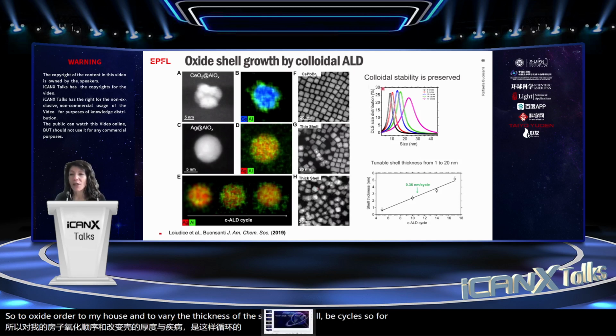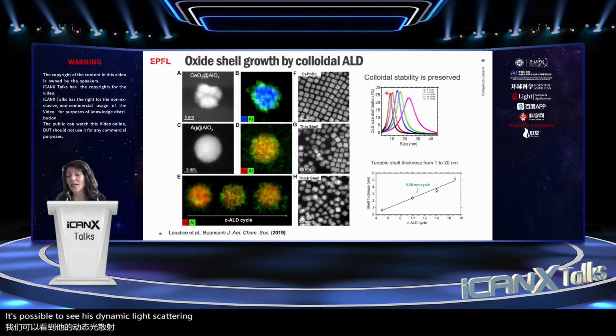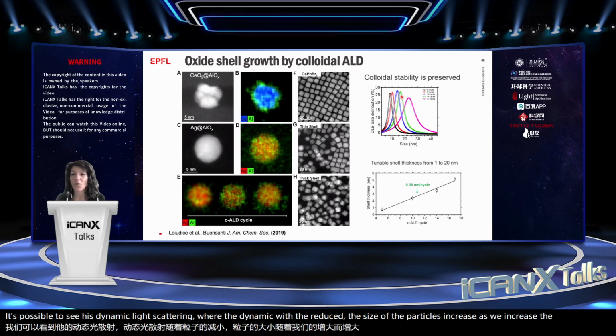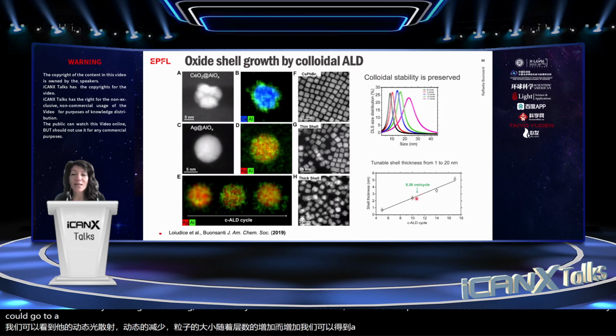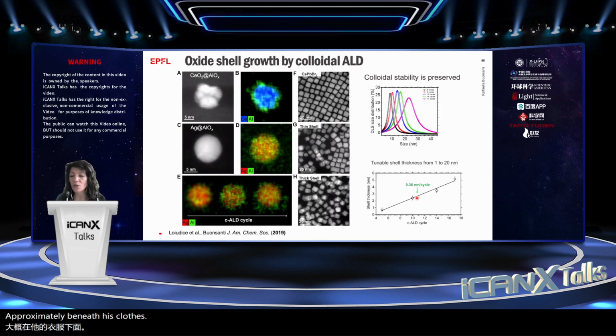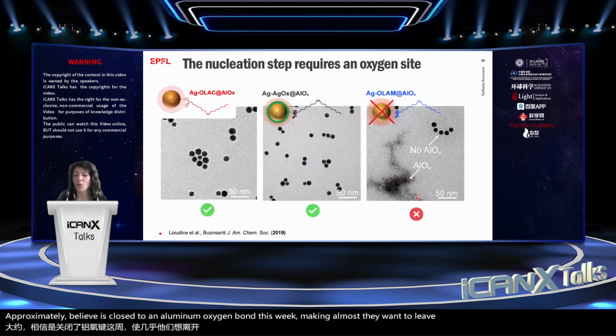So, for example, here what is possible to see is dynamic light scattering, where the radius, the size of the particles, increases as we increase the number of layers. We could also estimate the growth per cycle, which is approximately close to an aluminum-oxygen bond. So we are making almost a monolayer per each cycle.